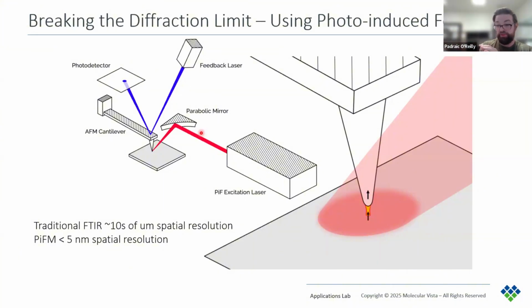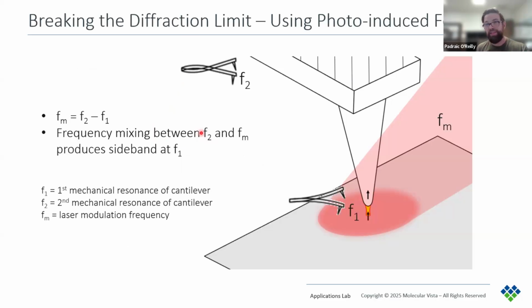less than 5 nanometers. So on a slightly deeper level, PiFM is a non-contact bimodal AFM technique. Being non-contact means that we will not damage or contaminate the sample. And being bimodal means that we can simultaneously record the standard AFM information, such as topography and phase and whatnot, along with chemical maps. So bimodal uses the first and second mechanical resonance modes of the cantilever for these measurements. These are eigenmodes, meaning they're independent of each other.